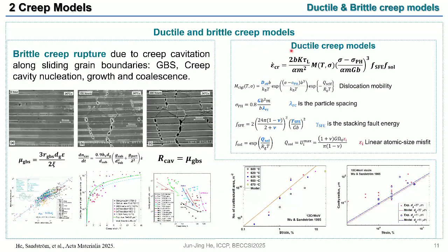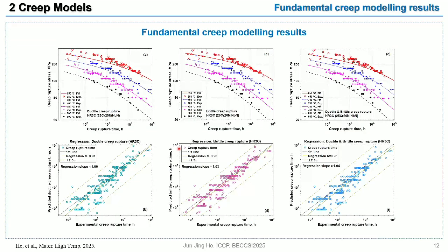This parameter is crucial for the solid solution hardening. And then we can go to the ductile creep models. In this model, we consider the dislocation mobility and the precipitation hardening, and also the stacking fault energy effect and the solid solution hardening, which is related to the lattice misfit. In addition to the ductile creep models, the brittle creep rupture due to creep cavitation along the sliding grain boundaries was also modeled, and this involves the grain boundary sliding models and the creep cavity nucleation and growth models. Then with all these models available, we can predict the creep rupture of the materials.